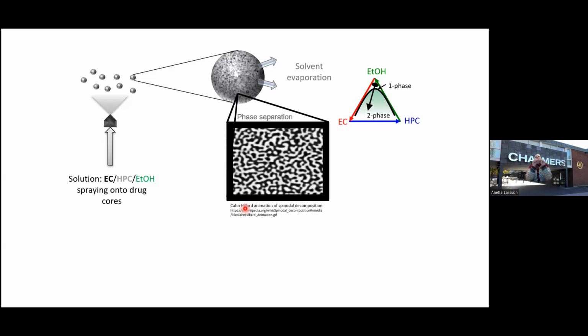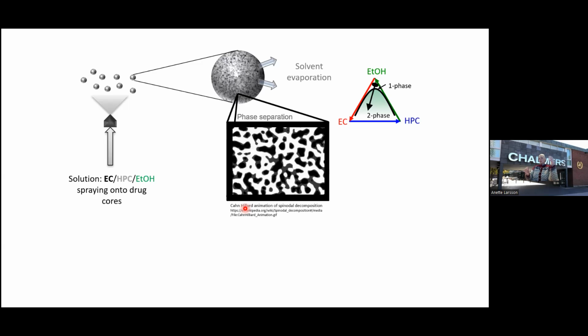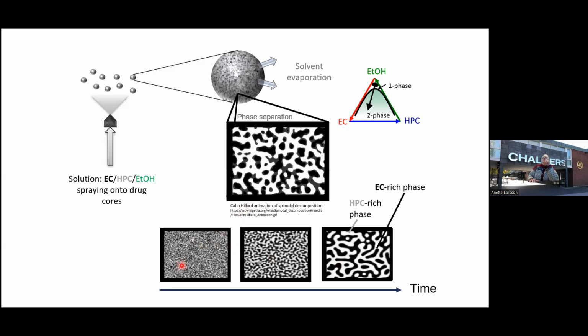But you can see here that the phases start very small, and then they develop, and the phase regions become larger and larger. And then one can lock them in one case. And then you can use this and lock them at different times. And that depends on, for example, the viscosity. If you have high viscosity, then you can have an arrested morphology of the coating. So here we have different times, locked at different times, the spinodal decomposition can develop for different lengths of time, and therefore it is locked at different structures. So we have the HPC-rich phase here and the EC-rich phase here.